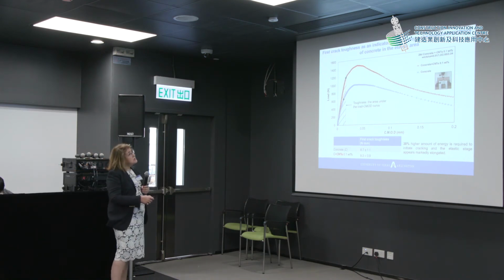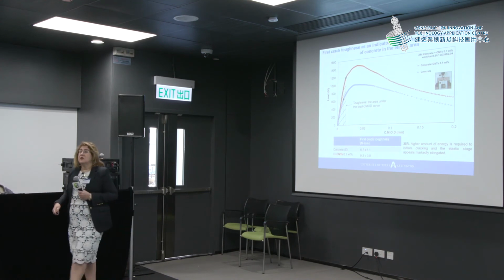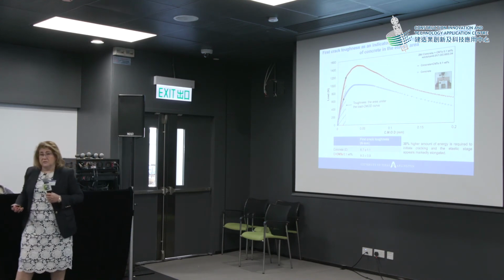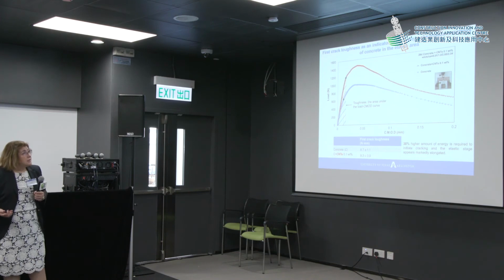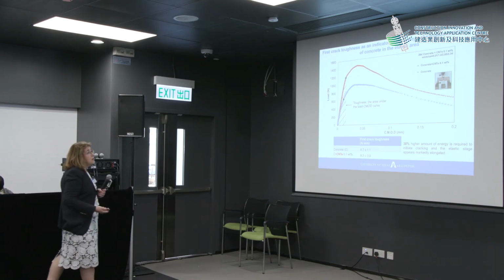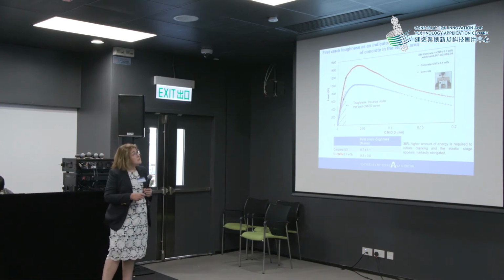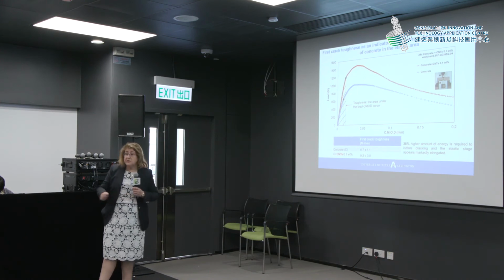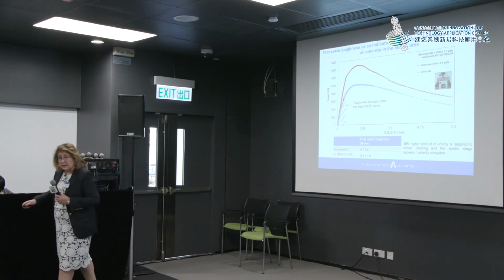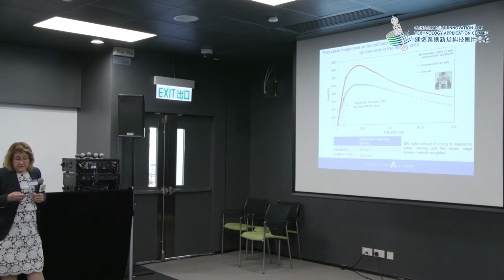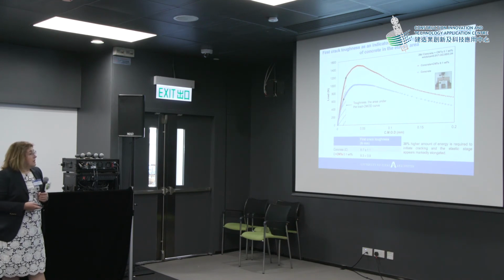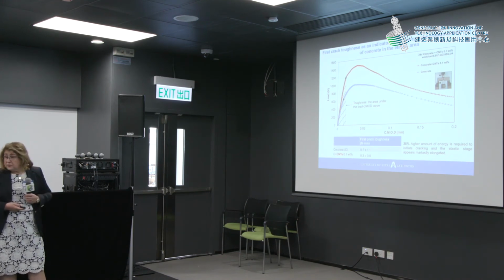And we were also able to identify the first crack strength and the first crack toughness. And the first crack toughness is an indicator of the ductility of the material, of the energy absorption capability of concrete, only that we are still in the elastic area. We haven't moved into the post-cracking area after the concrete moves after the first crack.